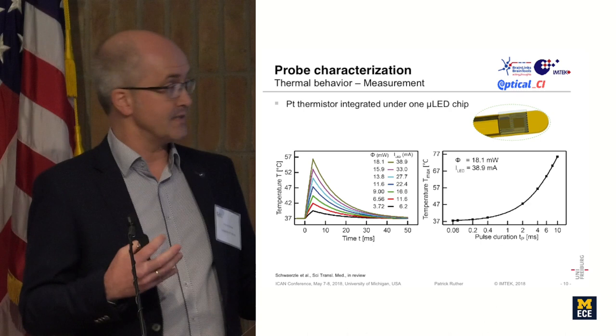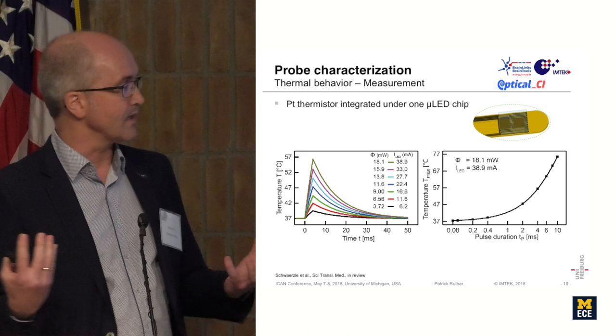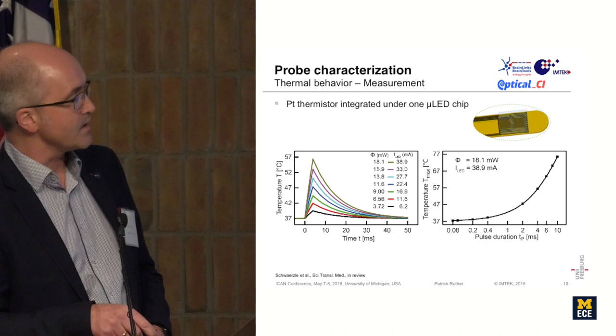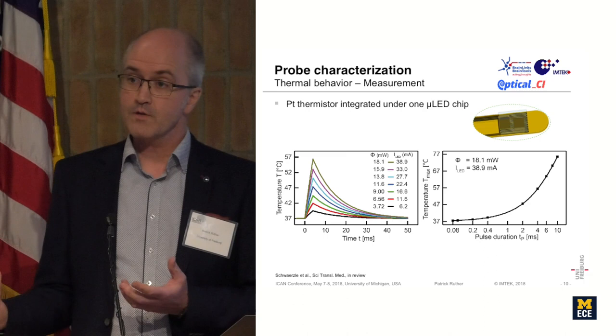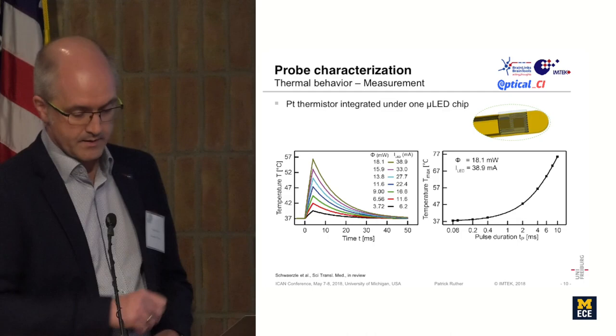And these are fairly high. You see here almost 40 milliamps are used. We power them at the limit that is doable. Now, what we clearly see is that dependent on the pulse duration, we get a temperature increase of 40 degrees. This is, of course, nothing that you would like to have in the body itself, but in this case, it's the temperature just under the LED.